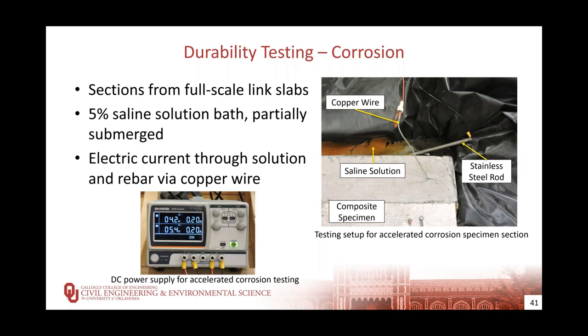Looking at the photo on the right, the current will run through the copper wire to the reinforcing steel within the specimen, which will act as an anode, and then through the concrete pore water solution to the saline bath, then through the stainless steel rod, which will act as a cathode, then back to the power source.